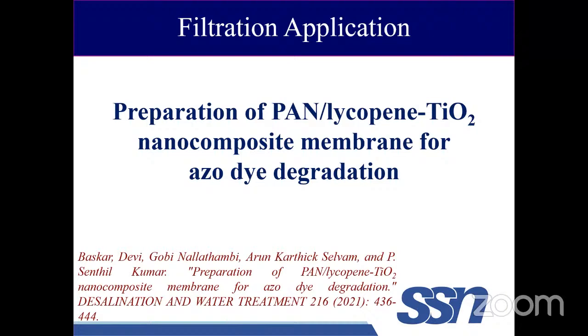Another disadvantage is, whenever the textile industry utilizes these photocatalysts, recovery of these photocatalysts after the photocatalytic activity is quite difficult, because they are putting these powders in the dye solution, which will degrade, and again they are putting these waters in the water bodies. Again, these TiO2 are going to contaminate or cause pollutants, right? So in order to avoid that, we have prepared a membrane-like structure utilizing nanofibers, in which we have doped these TiO2, and we tried converting these TiO2 nanoparticles into a visible photocatalyst by doping lycopene.